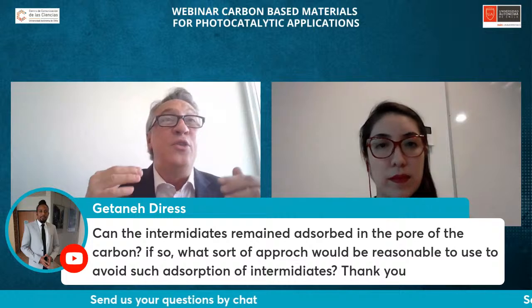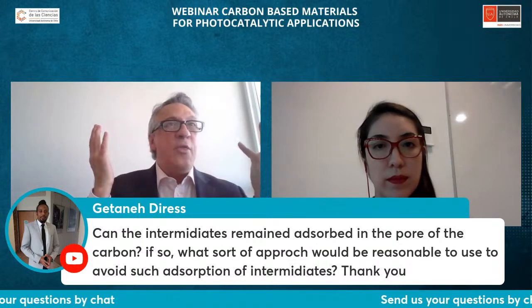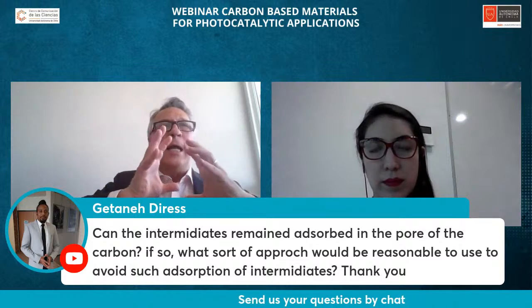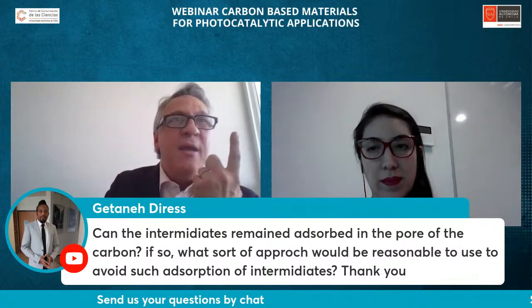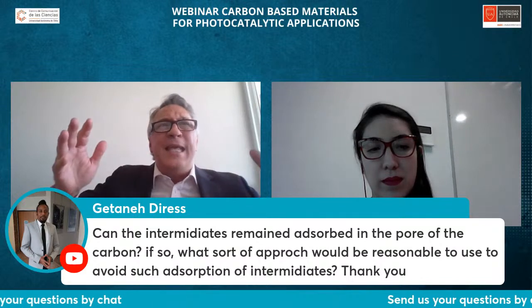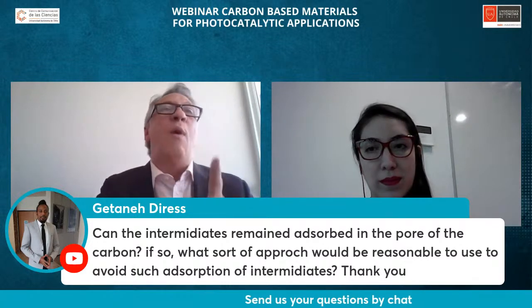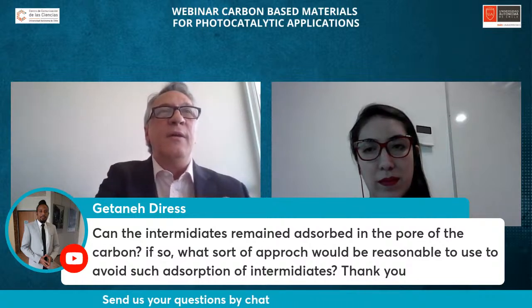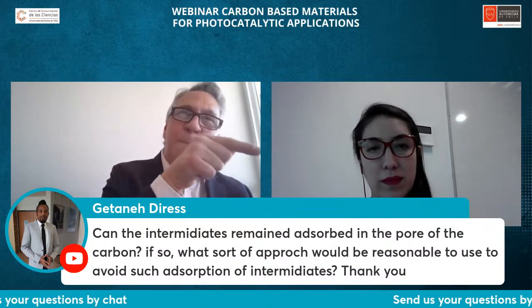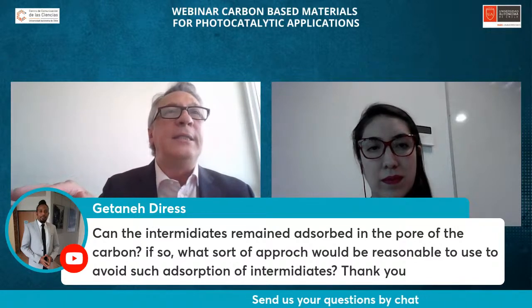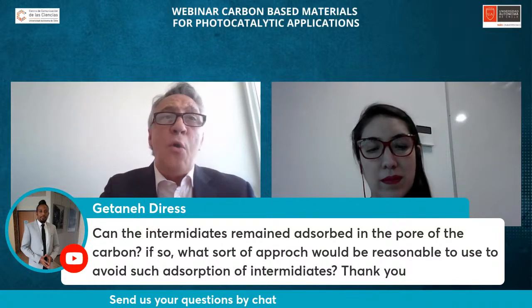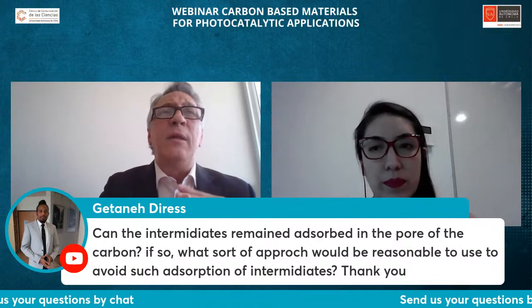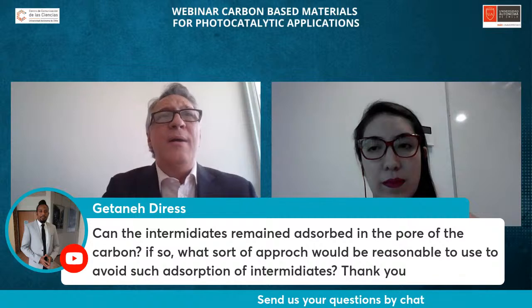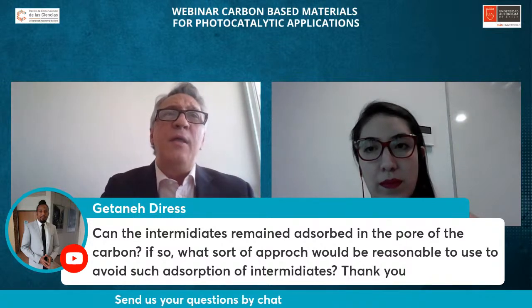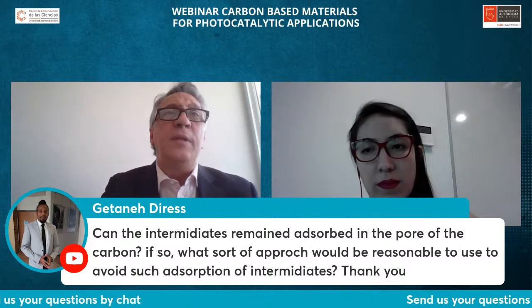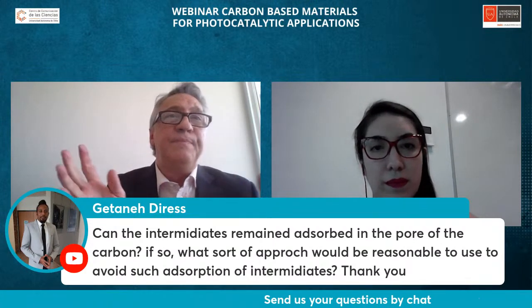It's crazy, because when you start to form intermediates, you can think about, in the case of a dye, it starts to fragment, and from one molecule of dye, it starts to promote the formation of 3, 6, 9, 12 fragments from only one. And if they start to compete with the original pollutant for the active adsorption sites, the catalyst is deactivated immediately. So it's very important to know exactly what the types of intermediates are, because they will affect, of course, the reactivity of the original molecules. Okay.